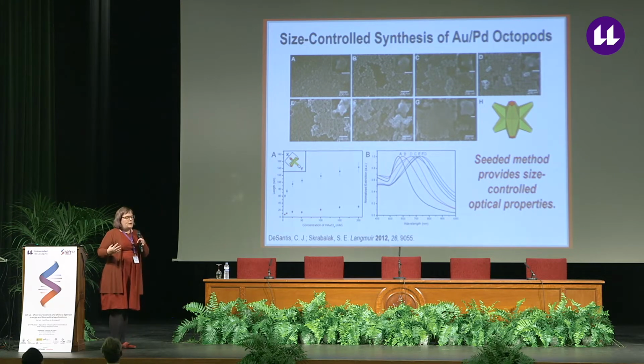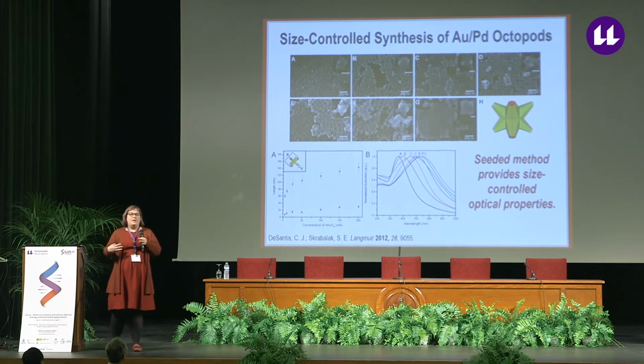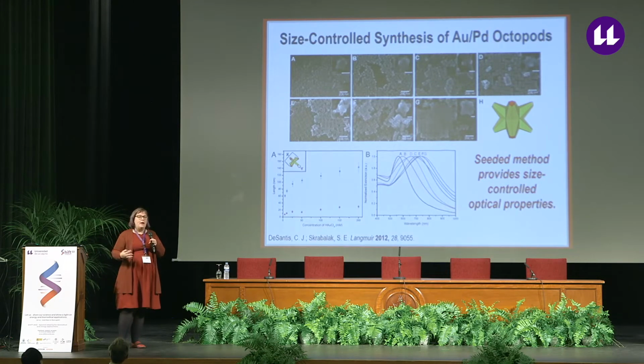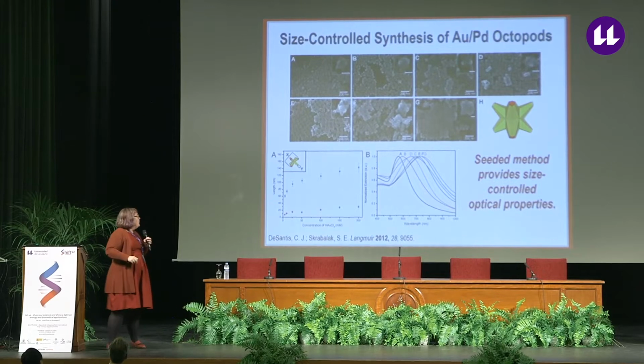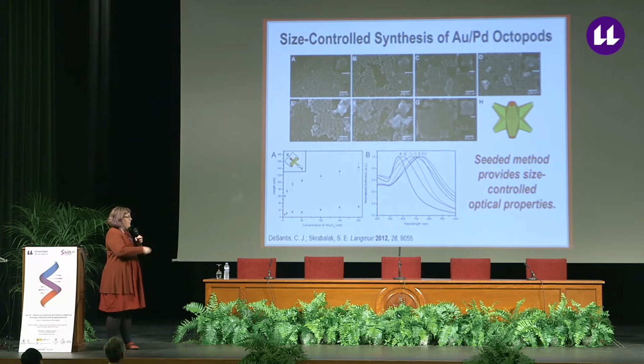So if you're familiar with plasmonics, you might think, well, this is crazy. Palladium, it's a really poor plasmonic metal. But when coupled with gold, a good plasmonic metal, and just a small amount of palladium, you can get well-defined localized surface plasmon resonances that can be tuned throughout the visible and into the near infrared.